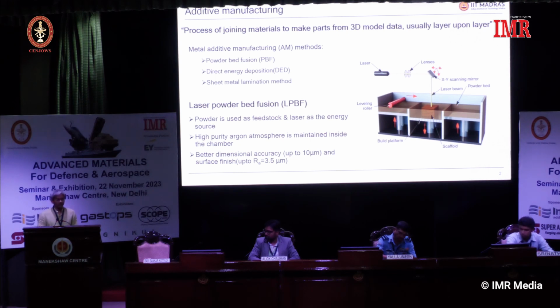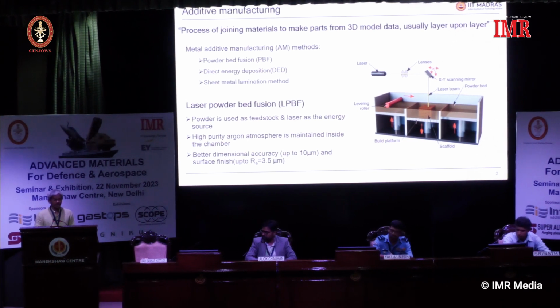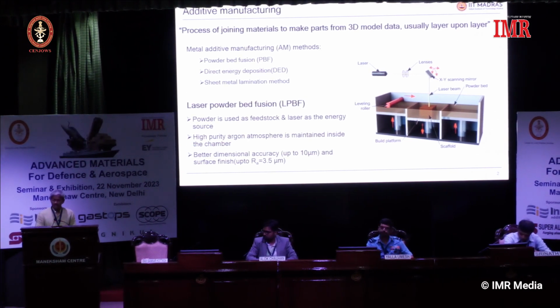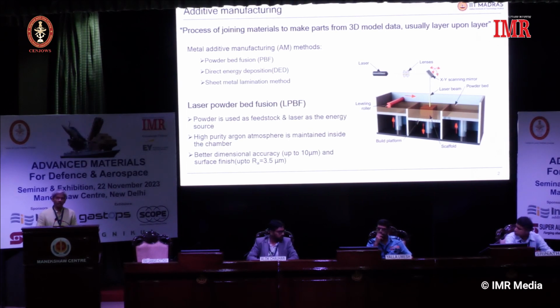LPBF, simply the laser powder bed fusion, essentially uses powder as the feedstock and a laser as the energy source, with a high purity argon atmosphere maintained inside the chamber. The advantage of LPBF is that you have better dimensional accuracy and surface finish. That's the diagram shown on the right side, which shows a powder bed here, and the build plate on which it happens.